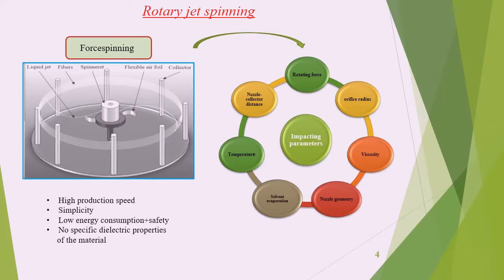Rotary jet spinning or force spinning is a simple and versatile method which is widely used for the fabrication of metal oxides for gas sensing. It can be used to fabricate microfibers to nanofibers by using centrifugal force to realize high rate production. The structure of the ultrafine fibers can be conventionally adjusted by changing experimental parameters such as rotating force, orifice radius, viscosity, nozzle geometry, temperature, and solvent evaporation.